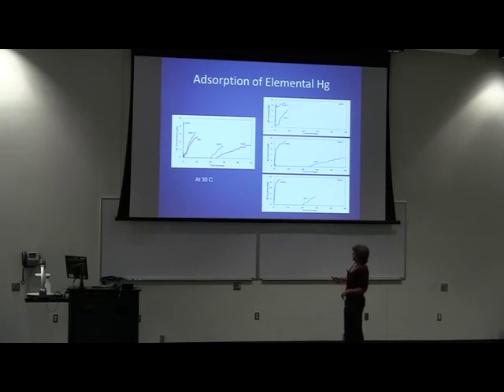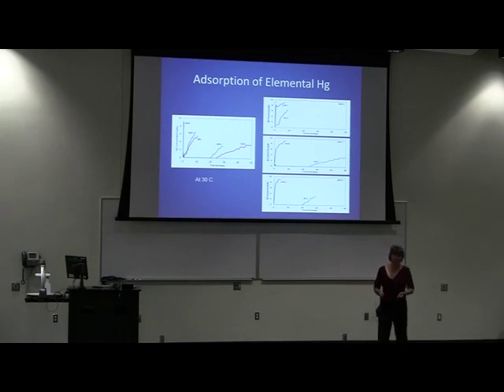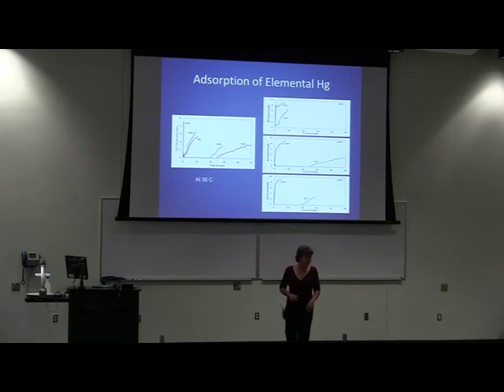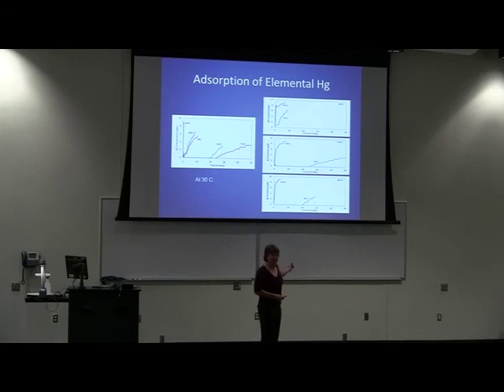But the question is, this is a BPL, and remember that has a surface area of 1,100 square meters per gram. And the fact that the breakthrough happens in these two de-inked paper sludge samples at a much later time, I have to ask why. These surface areas are 50 square meters per gram, and this has a surface area of 1,100. So it's not just surface area. So you have to ask yourself why. I see a lot of you starting to doze, but this is what people do when they do research. They get data, and if it doesn't make sense to them, they have to ask why.